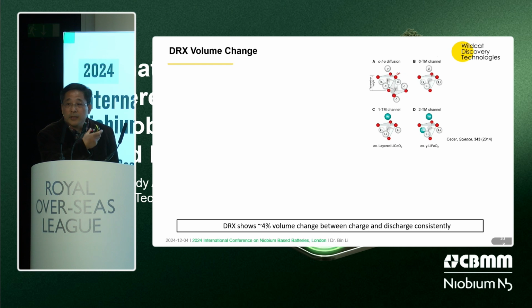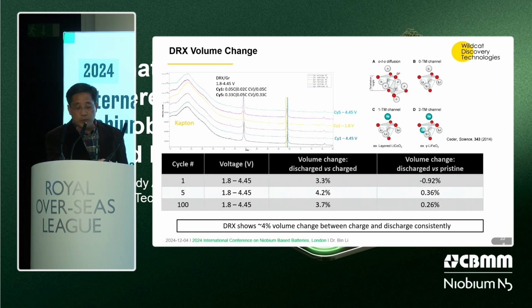So the last one is about the volume change. As I mentioned, because of the lithium diffusion, there's a small volume change. We also demonstrate that. You see here the cycle number with different charge voltage windows. You can see between charge and discharge, you get a 3.3% volume change. Even at five cycles, around 4, and even at 100 cycles, still 3.7% between charge and discharge. That's the swell of your battery.